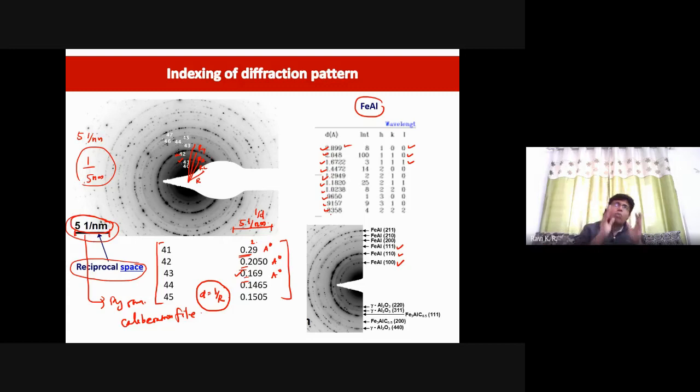See, exactly what we did in the X-ray diffraction when you have software or a JCPDS file or anything. From there, you can simply compare it. So what you can get, instead of 2 theta values, you can get it in terms of d values. Okay. So if you can do it through a d value, automatically you can see the same thing. Corresponding to this one, there could be some 2 theta value. The moment you fix a lambda, automatically you will get some 2 theta value.